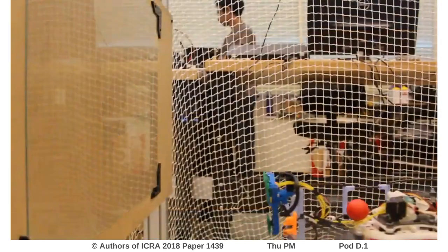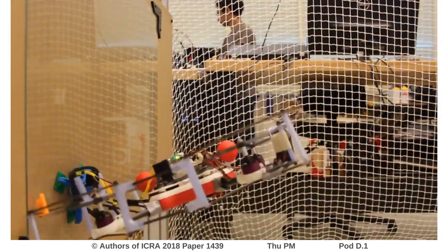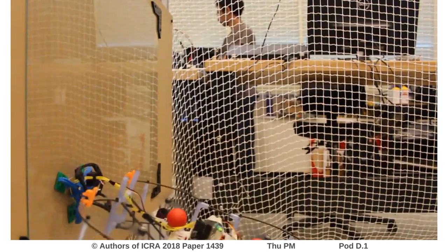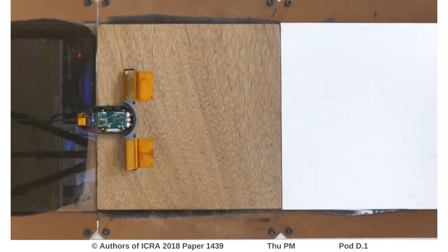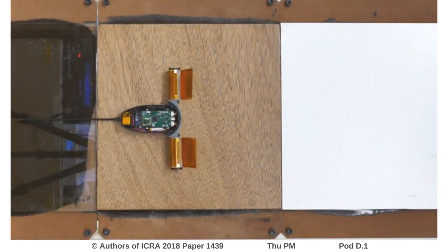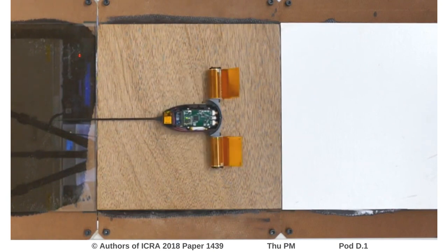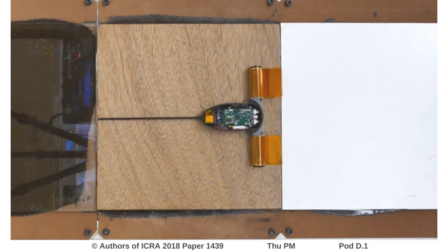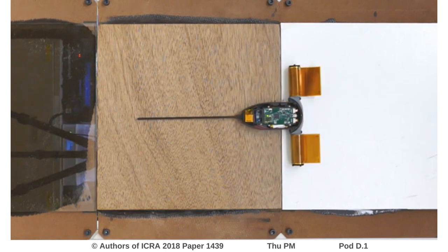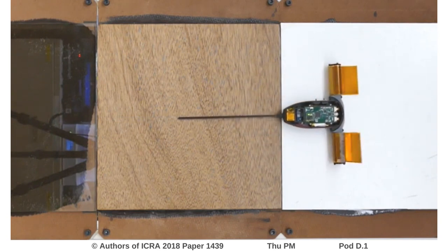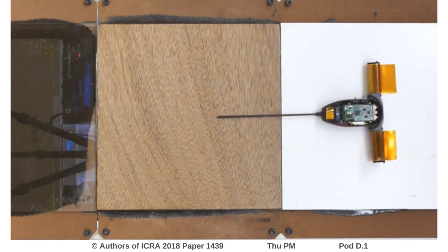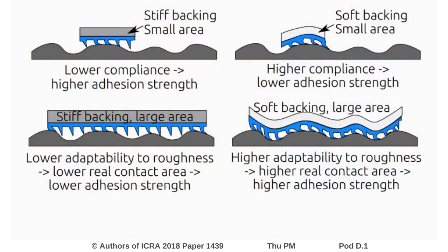It was previously shown that the maximum adhesion capacity of such adhesives is determined by the stored elastic energy. That is, lower the stored strain energy, higher the adhesion. However, adhesion capacity also depends on the real contact area, and the trade-off between the area and the stiffness has not yet been explored. Under ideal conditions, the contact area of a flat elastomer adhesive on a smooth substrate is equal to the pad's area.